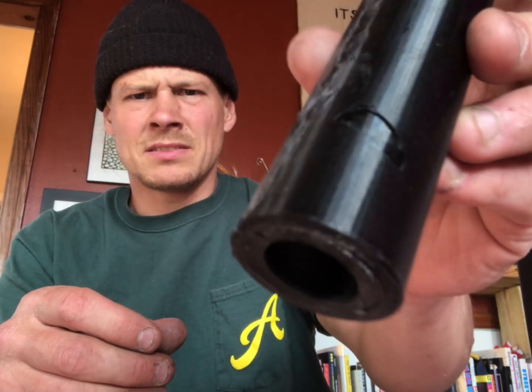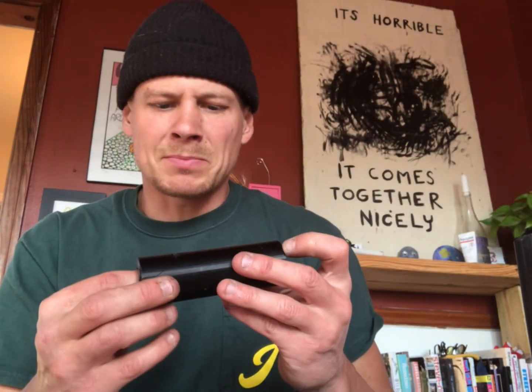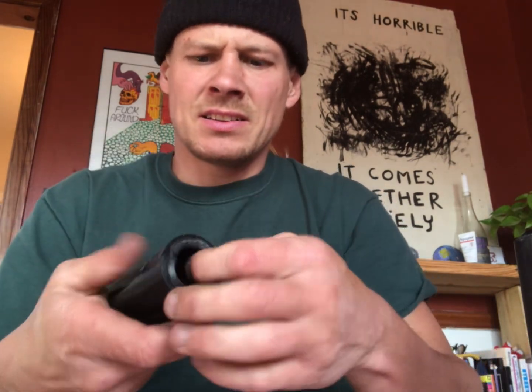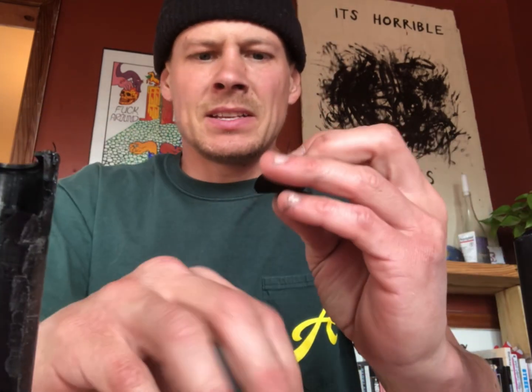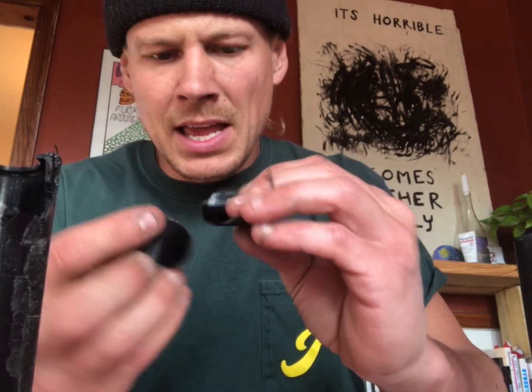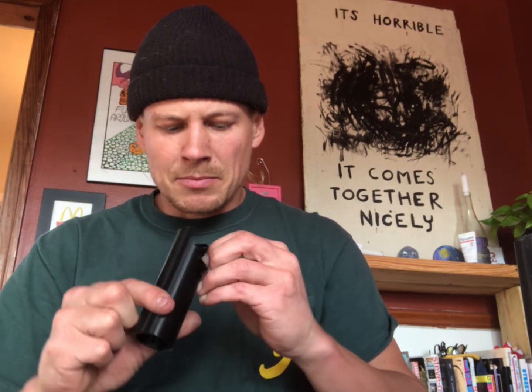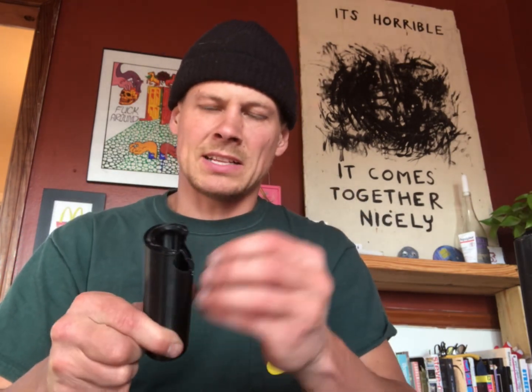Major difference here - and this one is proven. This is your PETG. I powerbombed this thing so hard I literally snapped my axle. You can see it's coming out the side - delaminating between layers. My settings: I read all about it, ran it slow, ran it hot. It still gave up on me. A lot of delamination. I have another one running right now, maybe we'll try it. It seems like when it hits, it delaminates layers - just a theory though.